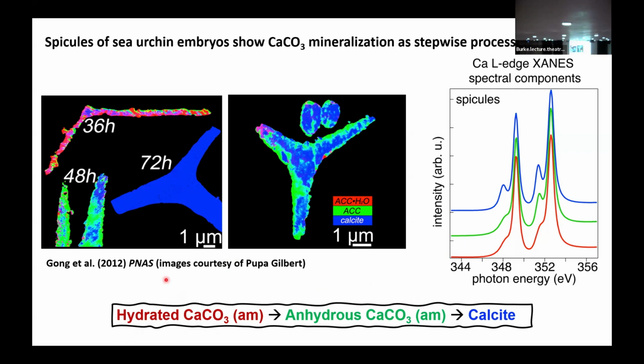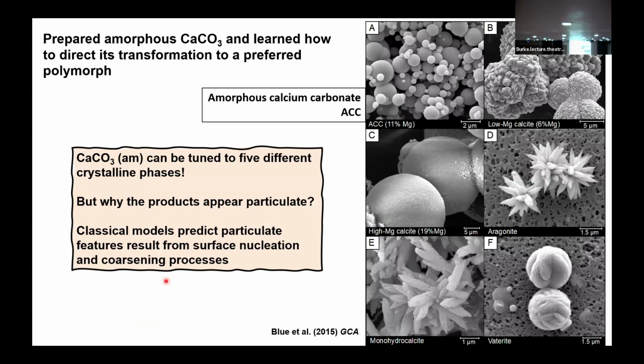And this reminds me of Dr. Bindi's quote on Tuesday, where he said that because these things can't happen, they didn't. And until someone called it out and said amorphous phases are important, really demonstrated to the community, people didn't see them, and suddenly they're seeing them everywhere. And so we did some simple experiments where we made things like amorphous calcium carbonate. And then based on insights from the literature and talking with people and biological systems, we were able to direct it to any of 5 different polymorphs: low-Mg calcite, high-Mg calcite, aragonite, monohydrocalcite, that was the most surprising one, and vaterite.